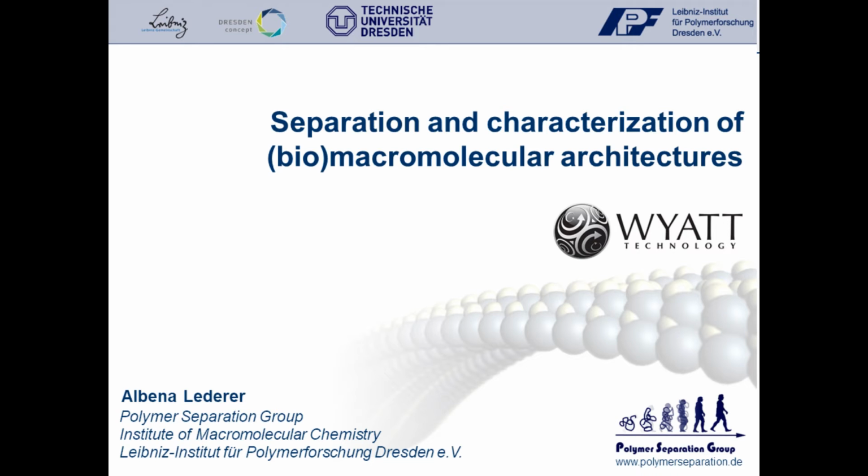And taking into account the concentration with a signal we are obtaining, the Rayleigh ratio we are obtaining from the mass detection, we can obtain information about all other parameters such as molar mass, radius of gyration, as well as the second virial coefficient. So concentration is, of course, very important in all these methods for the characterization, finally. I hope that this was the right answer. I understood the question properly.